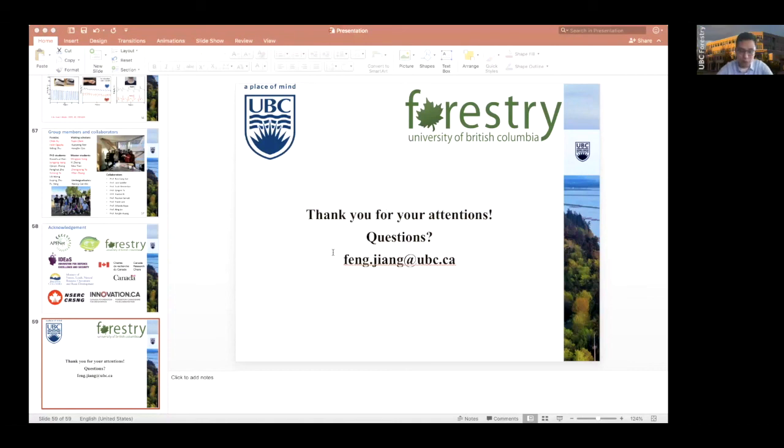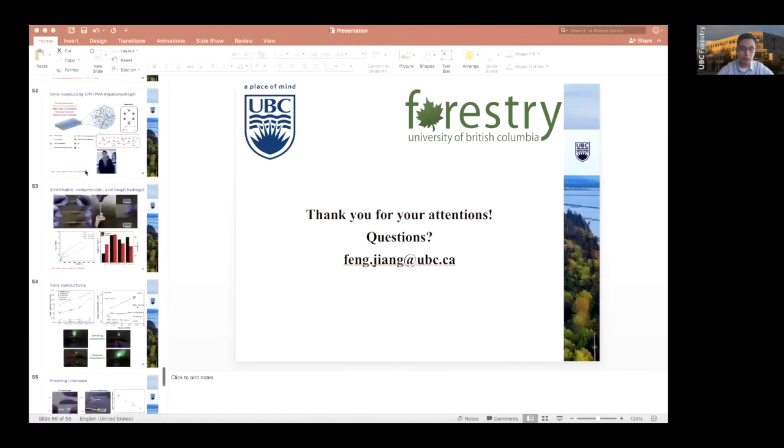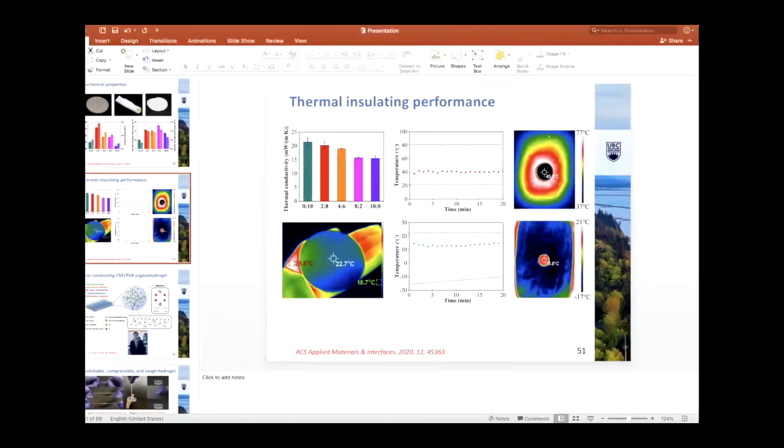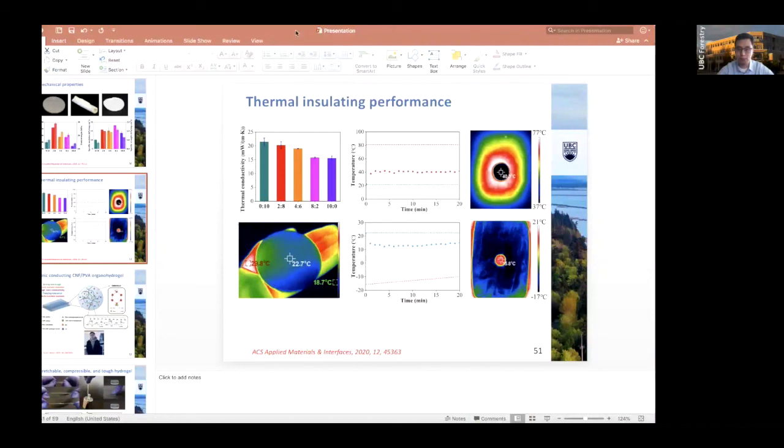Can you introduce how to prepare the Pickering emulsion in your work? The Pickering emulsion is well studied for nanocellulose, either cellulose nanocrystal or cellulose nanofiber. The one we use here has hexadecane as the oil layer, and cellulose nanofiber in the aqueous layer. We use sonication for different amounts of time. If you want details, you can check the literature; I think it's all described in ACS Applied Materials. So basically it is sonication of the oil with the present cellulose nanofibers.